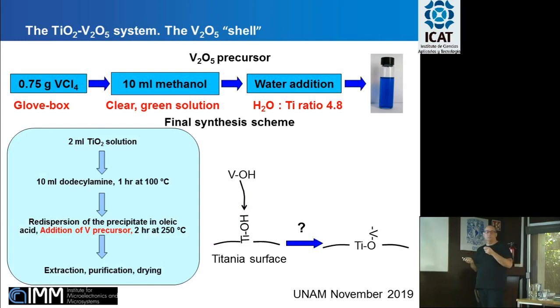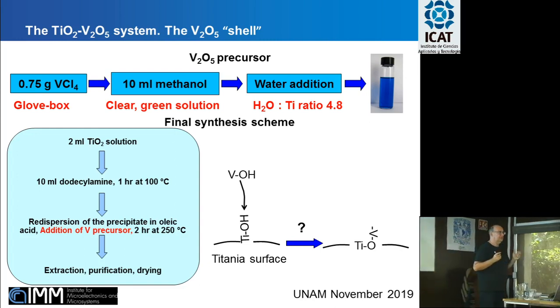How to do it? Once again, we have already our substrate, our precursor of vanadium. It is a chloride oxide. Why? Because the core was prepared with a chloride oxide, so it is hoped that if we use a chloride oxide, the same class of precursor for the surface, for the shell, there will be much more chemical compatibility than if using another precursor, and we can effectively carry out this surface deposition.